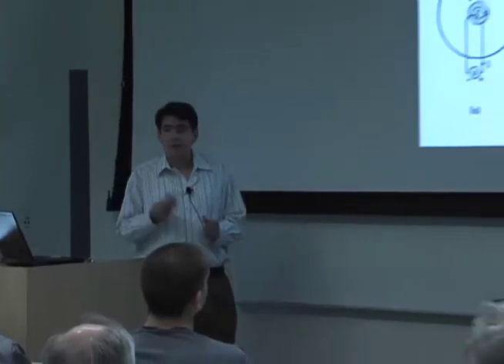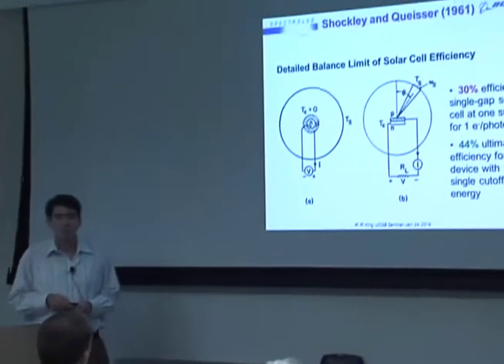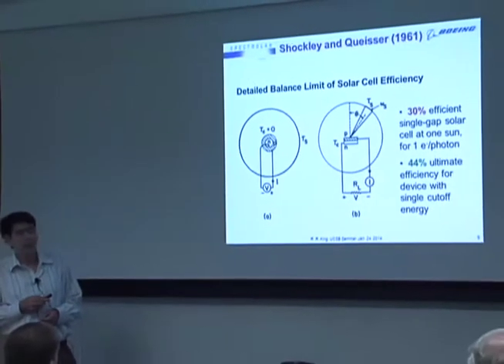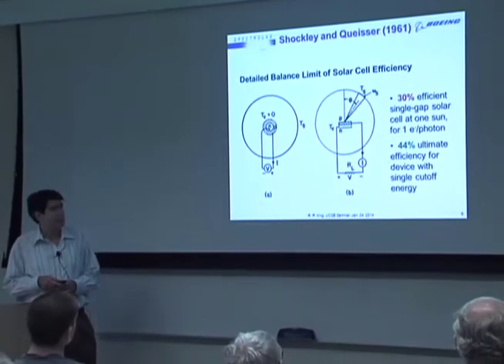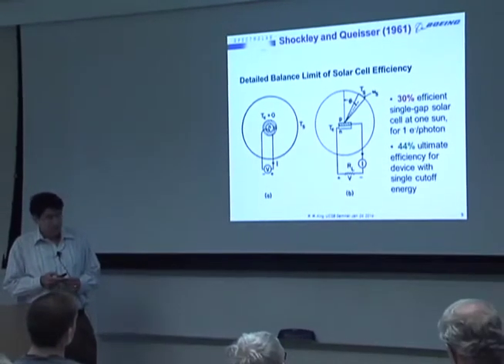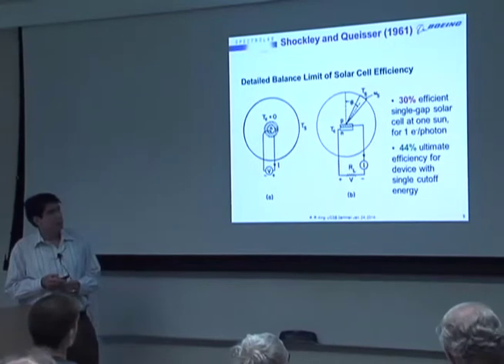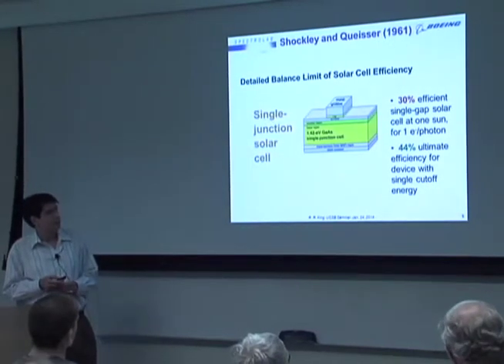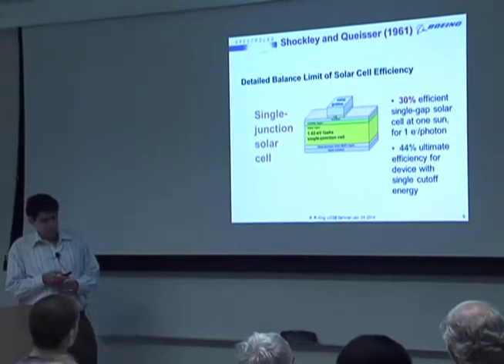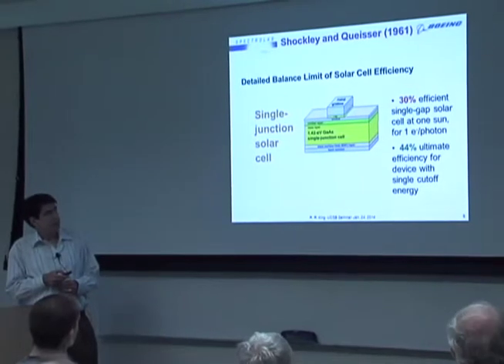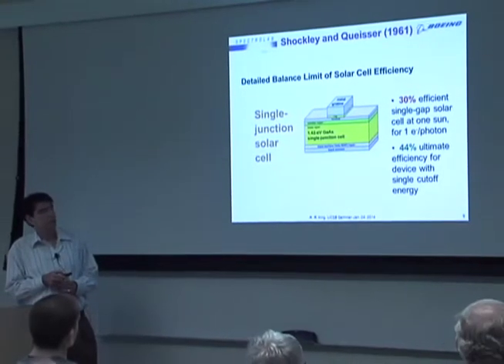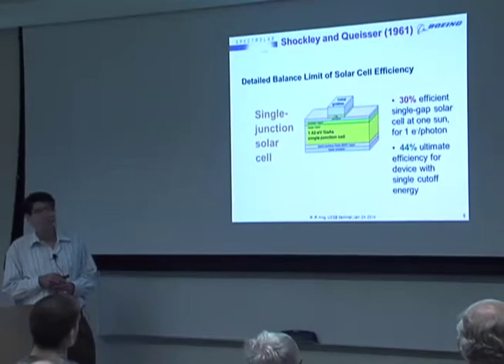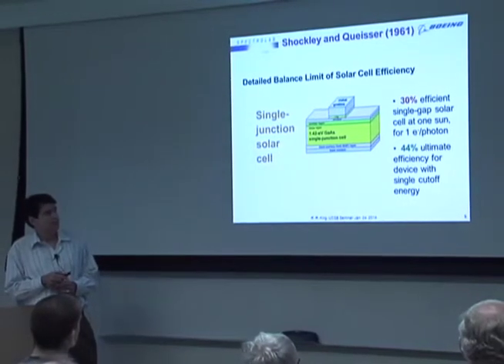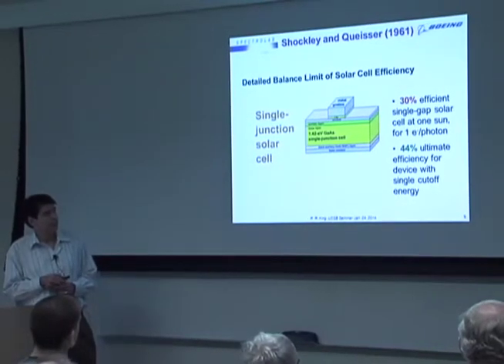So theoretical solar cell efficiency limits. Shockley-Queisser wrote a very famous paper that you're probably familiar with on the detailed balance limit of solar cell efficiency. And one of their assumptions was using single junction solar cells. For a single junction solar cell, the maximum efficiency one can achieve with the assumption of one electron hole pair generated per photon is 30%. And for a device with a single cutoff energy, it's 44%.